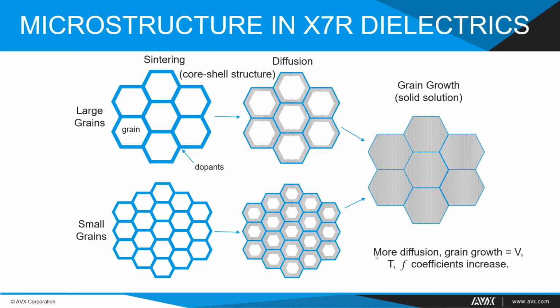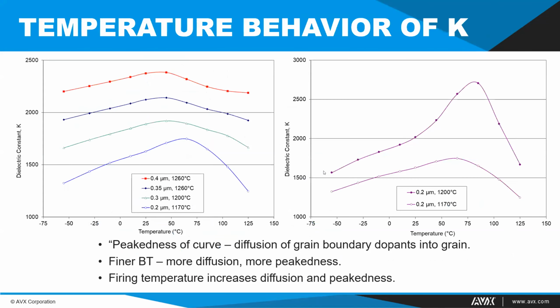So the important things to notice here is, as we diffuse more material in here, the material that's in the shell region becomes broad, and that material can impart temperature and voltage behaviors that are not desirable. So in many cases, it's important to have a tight grain boundary of materials if possible. The next slides will kind of illustrate how that process goes along.